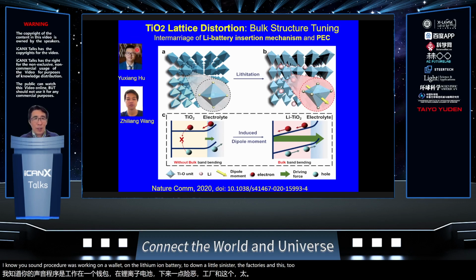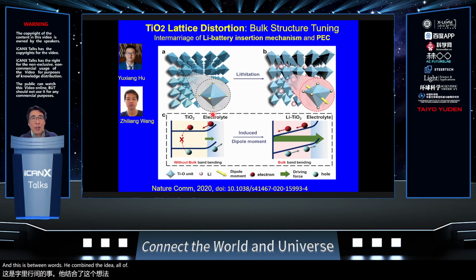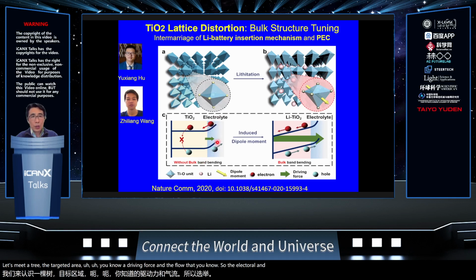And these two young fellows discussed and merged the idea of the lithium-ion intercalation mechanism with the photocatalyst. The idea was to provide some built-in electric field into the system. If you look at the common photoelectrode, particularly in the bulk, the bending is only on the interface between the bulk phase and the electrolyte. That means the charge carrier driving force for the electrons and holes is not that significant.